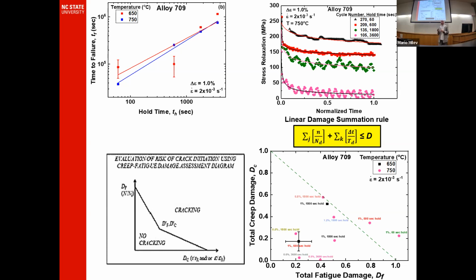Each material has an envelope which separates non-cracking from cracking. It takes many, many years to develop such an envelope, with a lot of data points, but we have preliminary data points for Alloy 709. There are envelopes developed for 316 stainless steel, and super alloys like 617. Here, for creep versus fatigue damage, we have preliminary data points at different temperatures, strain ranges, and hold times.